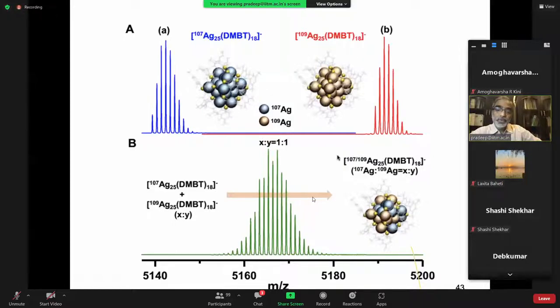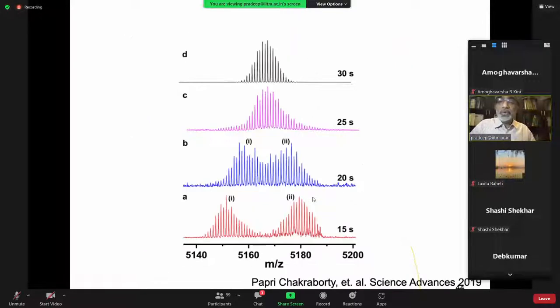You mix these two, this disappears completely. This also disappears completely. And what you get is a 50-50 mixture of these, similar to H2O and D2O mixing and giving you HDO. But she was in a position to measure this. The first mass spectrum could be collected in 15 seconds of mixing. 20 seconds, 25 seconds, and 30 seconds, this whole thing is gone.